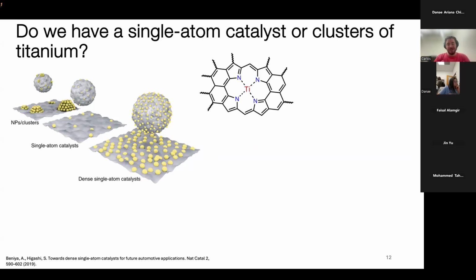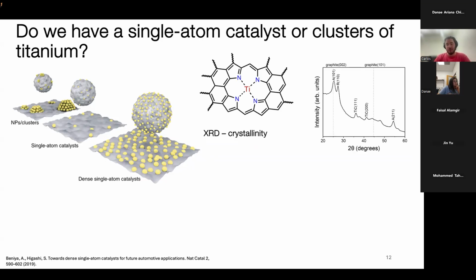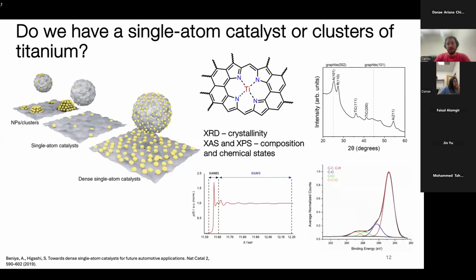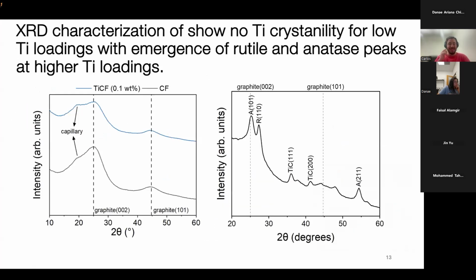So in order to answer this question, if we really have this structure, we use XRD to probe the crystallinity of our catalyst, and then we use XAS and XPS to probe the composition and chemical states that we have. And we can confidently say at the end of this, we know what the structure is. So I won't spoil it until I say it. But first, we did XRD.